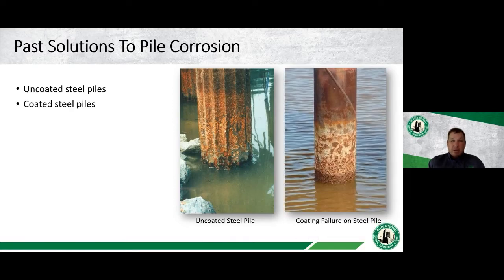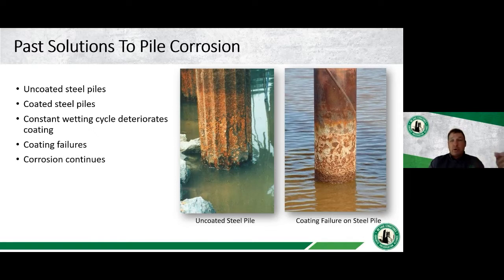The next thing that has been done is coated steel piles. As everybody knows, coatings are never 100% perfect. There are lots of holidays or pitting within a coating, and you eventually get a coating failure. As you get this coating failure, it becomes very aggressive, and sooner or later your coating is just going to have a complete failure. It's also very difficult to do any sort of repairs to your coating system, because you have to cofferdam or do something to that extent so that you can come in and repair your coating.